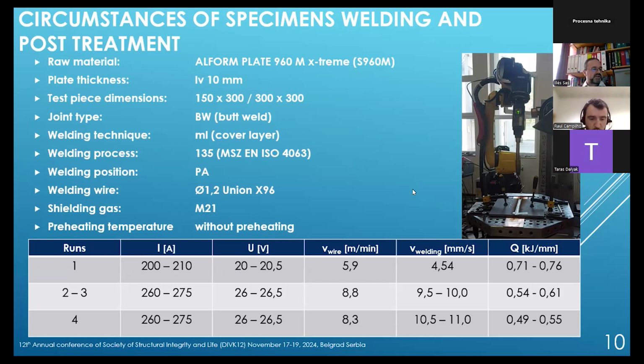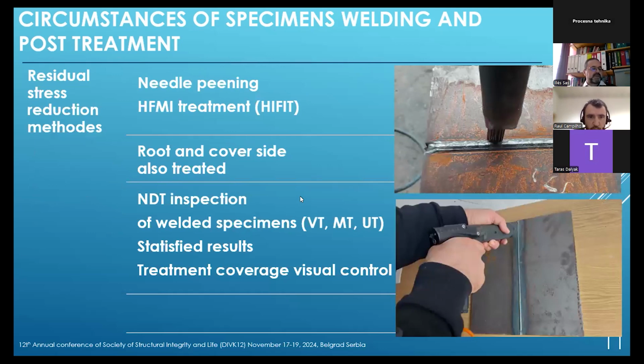You can see here the main welding parameters. We welded the specimens with 4 layers. Then we started the investigation with the residual stress reduction methods, needle peening and HiFIT, high frequency mechanical impact treatment. You can also see some photos: the top photos are from the needle peening method, where along the welding lines we apply the treatment, not only on the cover side but also on the root side. On the bottom photos we can see the HiFIT treatment.